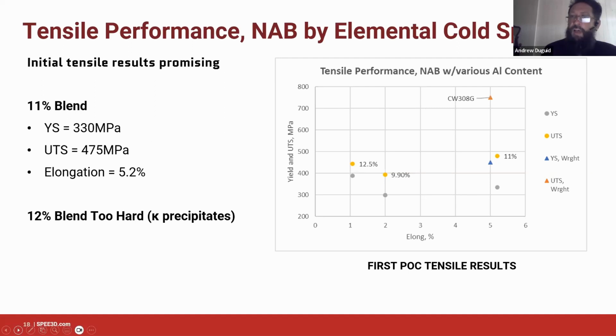That's for a material where we are using a conventional heat treatment, for want of a better term, just a conventional homogenize and sinter and an aging treatment. We've got something with a bit of a knockdown on wrought, but in the ballpark at 11%. Now you can see that the 9.9 data point is not so crash hot, and the 12.5 is really a bit awful. Well, it's quite strong, but it's terribly brittle.